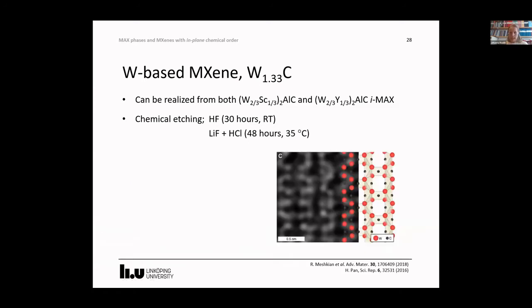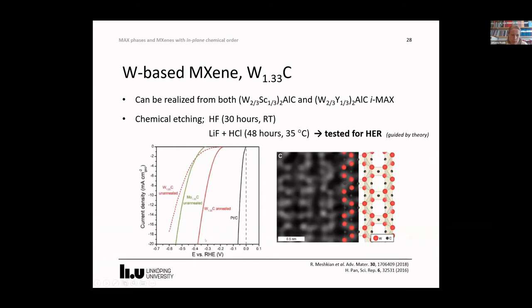This is what that MXene looked like in TEM, and guided by DFT calculations from the literature that predicted a high catalytic activity of a tungsten MXene, we decided to test for hydrogen evolution reaction. To place these results in perspective, we compared the tungsten MXene to Mo MXene and also to a platinum carbon electrode. The results showed that the HER activity is best for the annealed tungsten MXene. But it should be stressed that these were our initial results, and we've worked on improving the MXene quality since then, which has improved the numbers for the unannealed tungsten MXene to above the annealed tungsten sample. But this is work in progress.